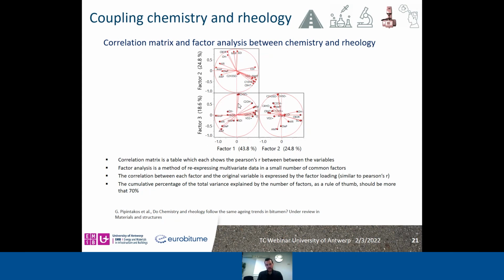Also, the length of the ray shows how extensive this correlation is, and the closer the parameter is to the y or x-axis of this circle, the more it shows if it loads heavily to factor 3 or factor 1, for example. From this graph, one can see that sulfoxide-containing fragments load heavily on factor 3, whereas all these chemical parameters load heavily on factor 1, and it was shown afterwards in more detail that all these parameters are able to distinguish the fast and slow rate phase.